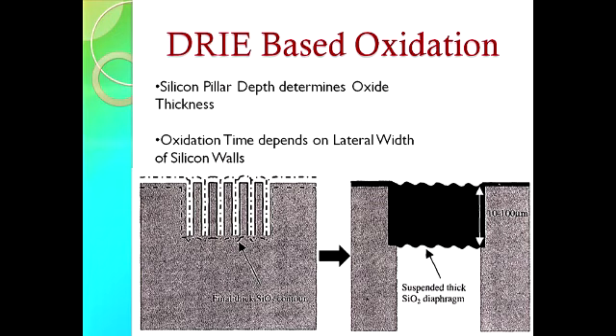Yes. So now we are doing two processes. We have to first etch this, then do oxidation, then do LPCVD, only when we have voids. If there are no voids, we don't have to do LPCVD. Versus just putting the wafer inside a furnace and leaving it for 20 hours. Yes, and we'll get a thicker oxide. So which one is better then? If we don't etch them and we place the wafer inside the furnace without etching, we will get an oxide layer, but we'll not get a thicker oxide layer because of diffusion rate constraints.